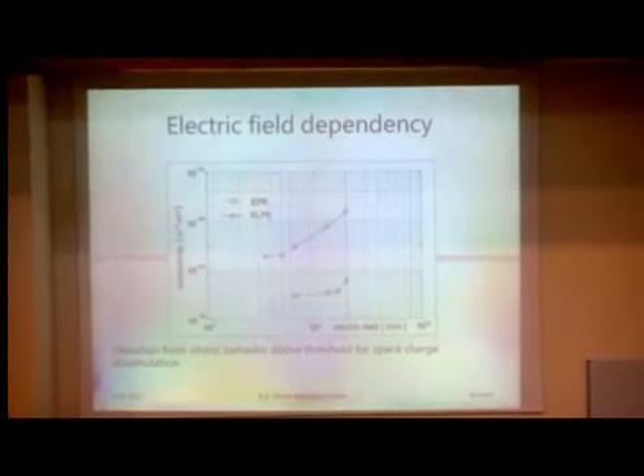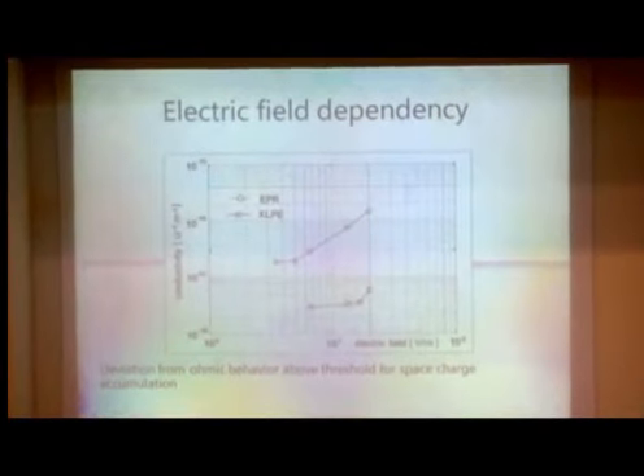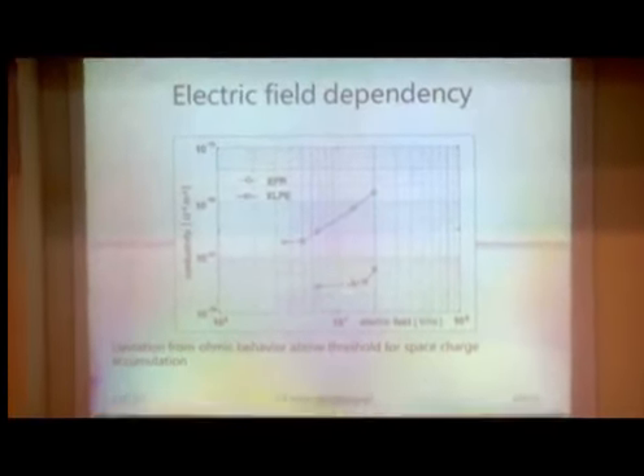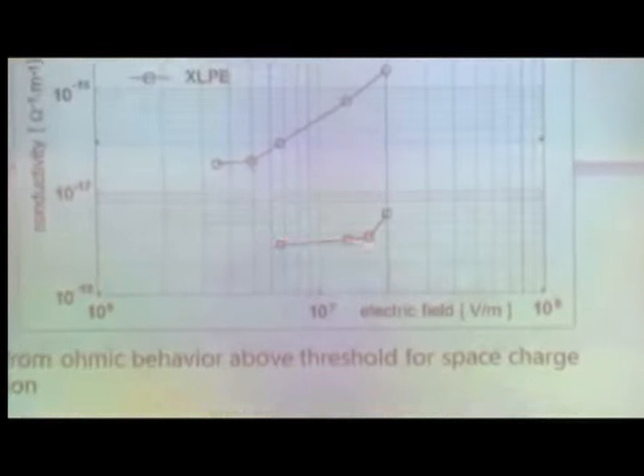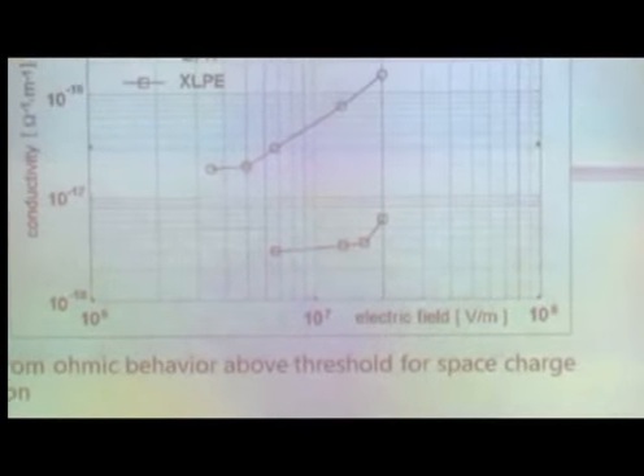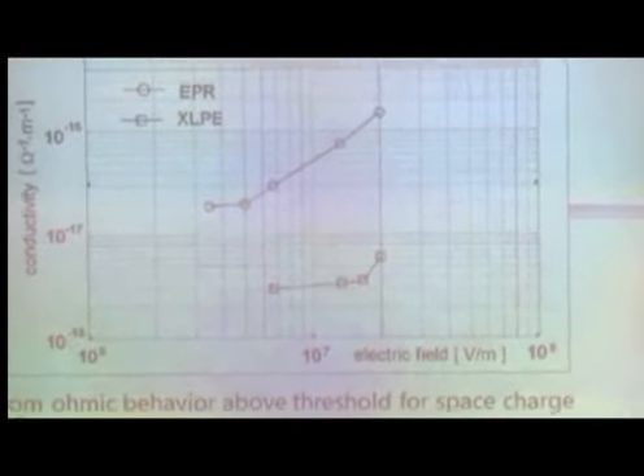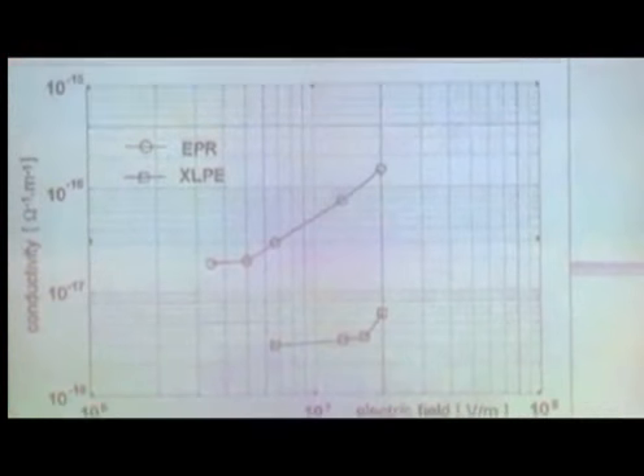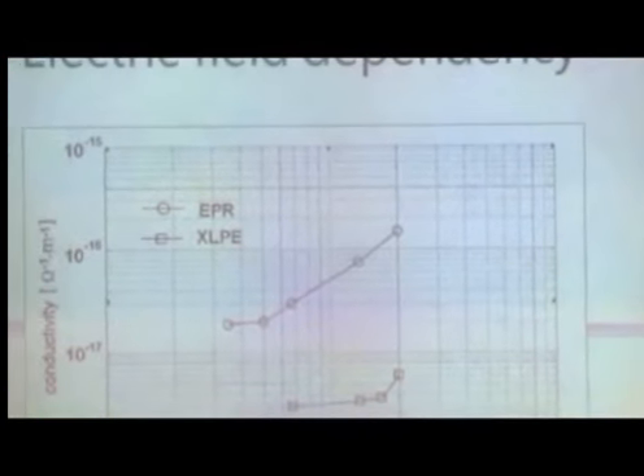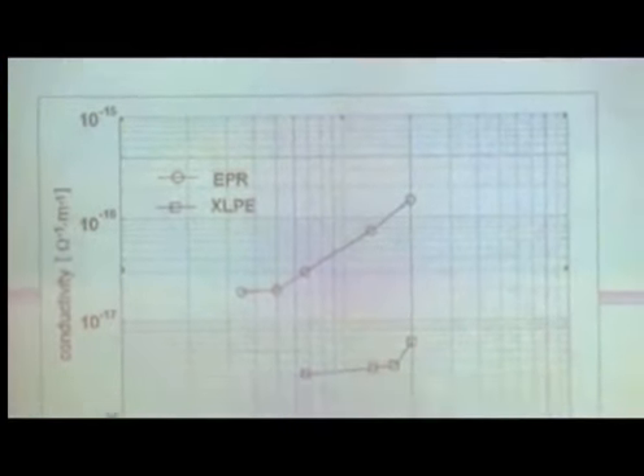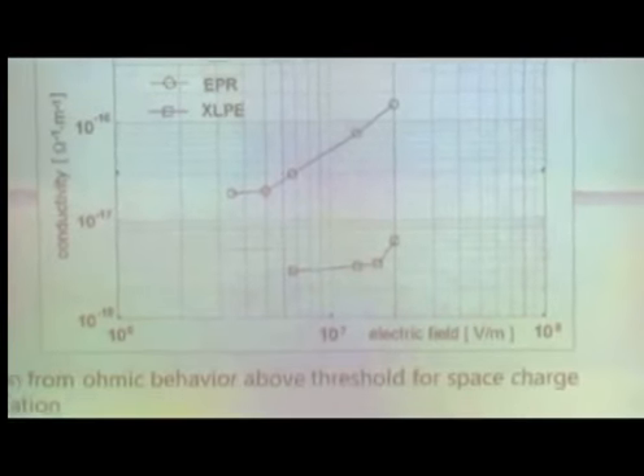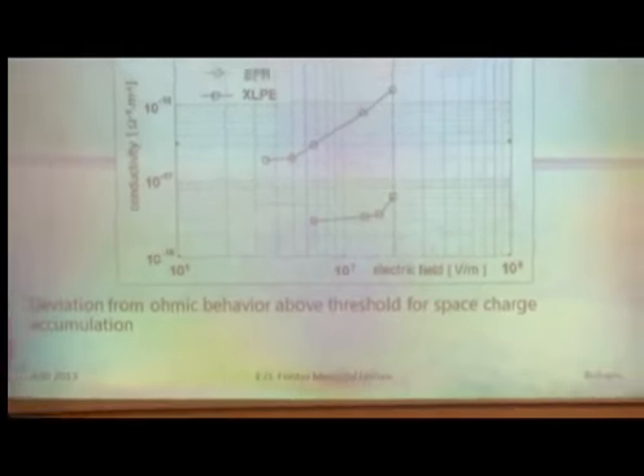For the field dependency, here it becomes a little bit more complicated. Here you see a plot of the conductivity as a function of applied field. Up to a certain value here, we have almost constant conductivity, ohmic behavior, easy modeling. But above a certain threshold field, the threshold for space charge accumulation, we see a deviation from ohmic behavior. And we have to deal with it in our model.